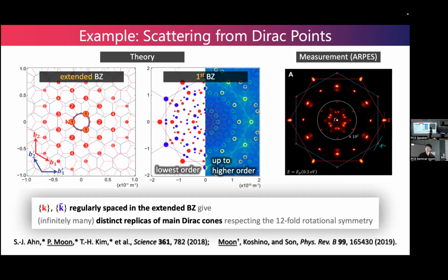And so the formula says that K, that point in layer 1, is expanded by the reciprocal wave vector of layer 2. If we map this to the first Brillouin zone, they are mapped to this point. And it is consistent with the ARPES measurements.